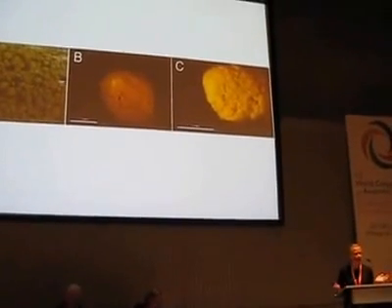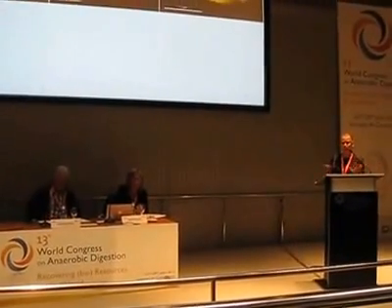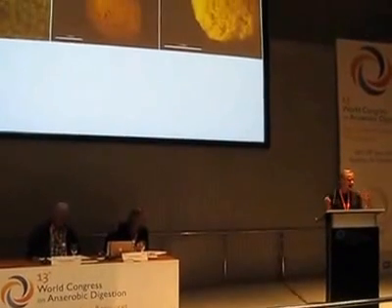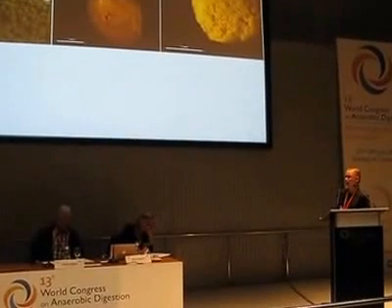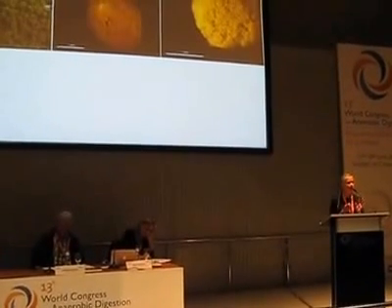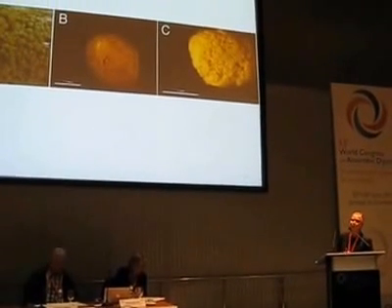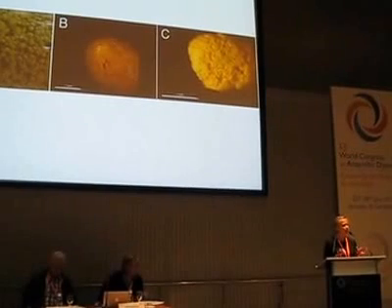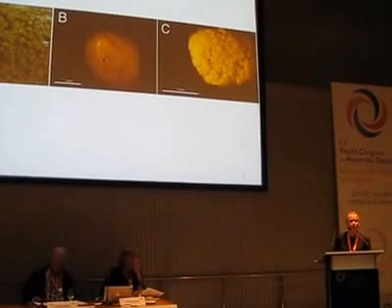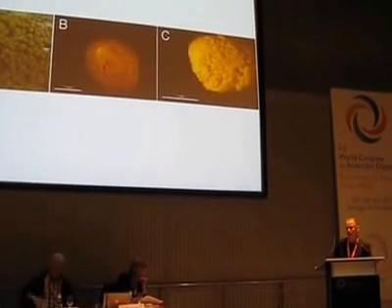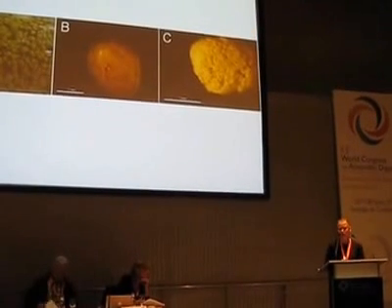About a year after we started our black water UASB reactor, a miracle happened. For the first time, under these conditions, we were able to biologically induce the precipitation of pure calcium phosphate granules. Here in picture A, you see these granules in the reactor covered by a biomass layer. In picture B, you see these granules separated from the sludge bed, rinsed and dried, having a diameter of 1 to 2 millimeters and an organic content of 30 weight percent. When we burn away the organics, we are left with these white calcium phosphate granules of similar diameter.